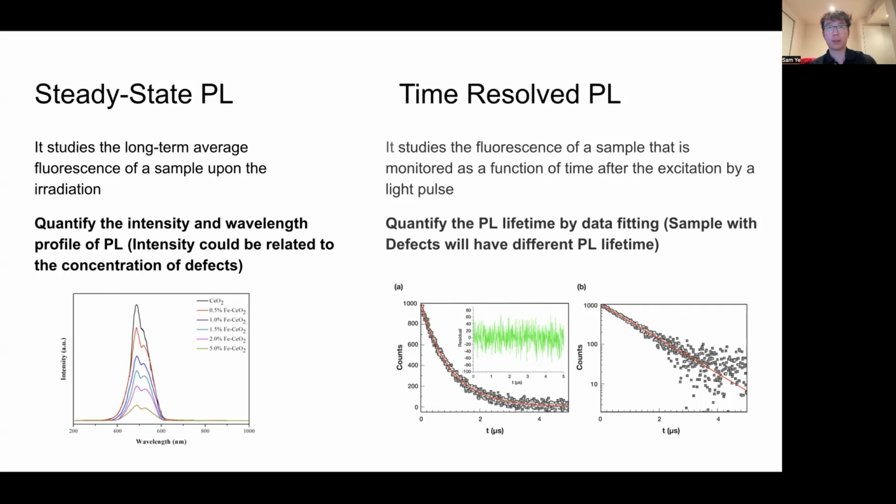The time-resolved PL quantifies the PL lifetime by data fittings. Using this information, we can potentially identify the type of defects and determine the concentration of defects, because the lifetime of defect-related PL varies from sub-nanoseconds, microseconds, and even seconds for different defects.